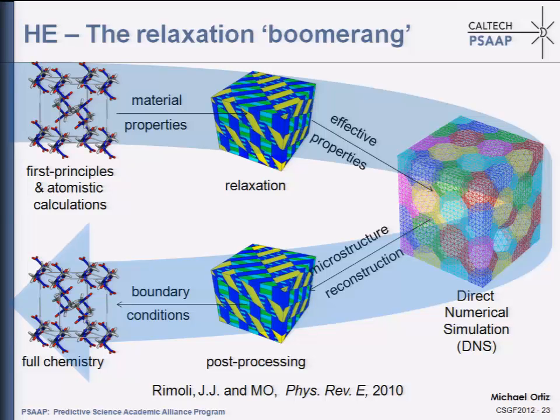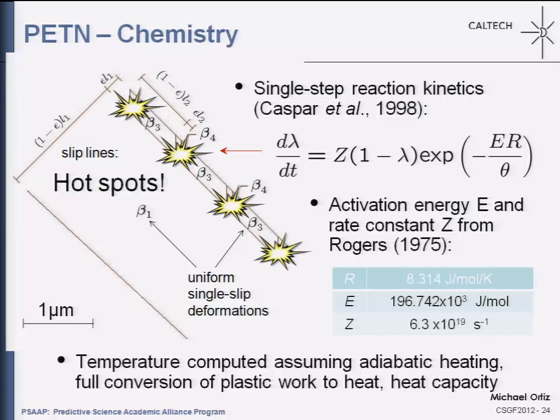So then we can go back at the post-processing stage, generate microstructures of interest, and then pass boundary conditions to our colleagues. Typically, the microstructures that you find are microstructures where you have extreme concentration of deformation at some points. So these are the hot spots. It turns out that the time scales in the development of these hot spots are of a microsecond. So if you go to somebody like Bill Goddard and say, please do a quantum mechanical calculation over a time span of microseconds, he'll say it's absolutely impossible.